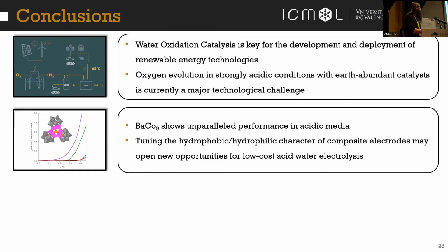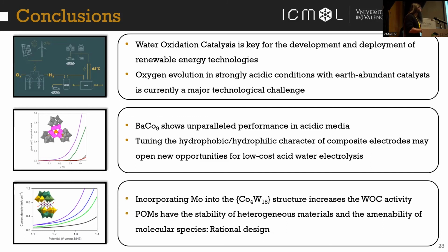So if we tune the hydrophilic character of our composite electrodes, it might open new opportunities to develop low-cost acid water electrolysis. And also, finally, that incorporating molybdenum into the structure increases the catalytic activity. And this also shows us that we can do bottom-up rational design of our catalysts to increase the catalytic activity.